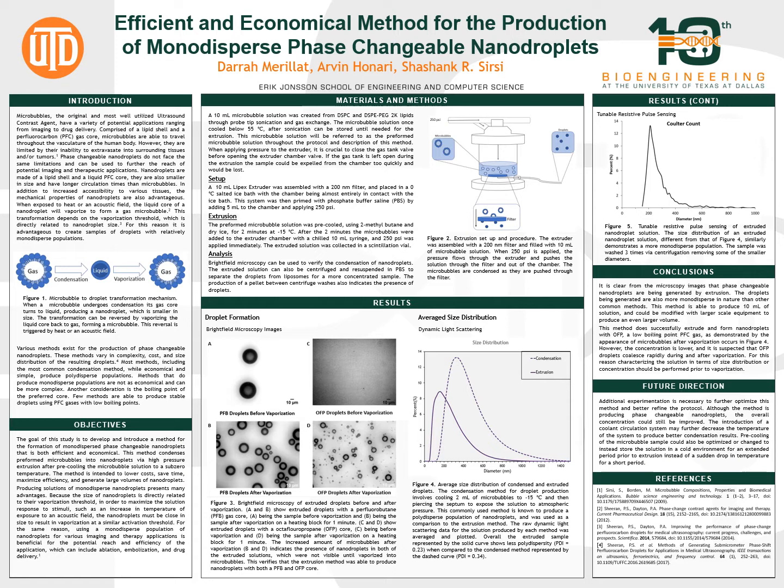Additionally, you have to take it a little bit with a grain of salt in terms of the microscopy, specifically with the OFP after vaporization, which is D, because we see a lot of coalescing immediately after, which is why the distribution is done before vaporization happens, before those bubbles coalesce. So in conclusion, this method does create a nanodroplet solution that is relatively monodisperse.